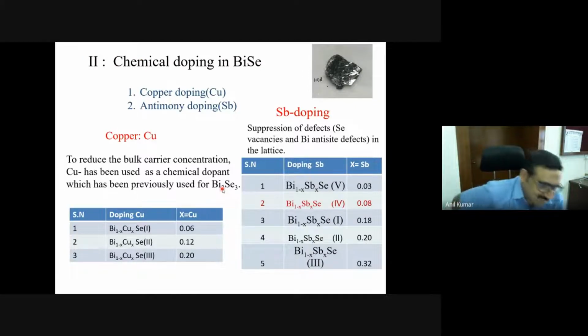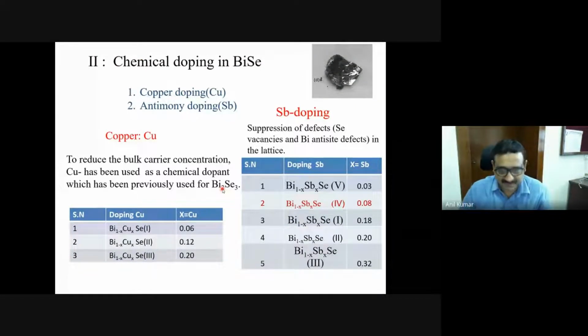Now, we started asking the questions, it's a new system. Nobody has studied this kind of system. So can we do chemical doping like what we did for the tin doping in the previous case? Our idea is to make a bulk insulating material. So far, our attempts on bismuth selenide, and we also made bismuth telluride, we never got bulk insulating material because of the self-doping. So then we started asking ourselves the question, can we do compensation doping and then see whether we can get bulk insulating material?